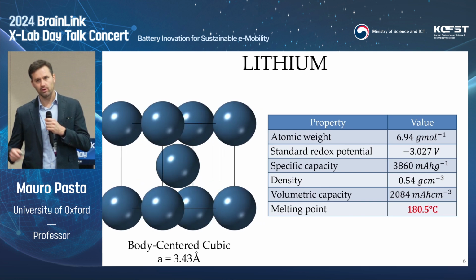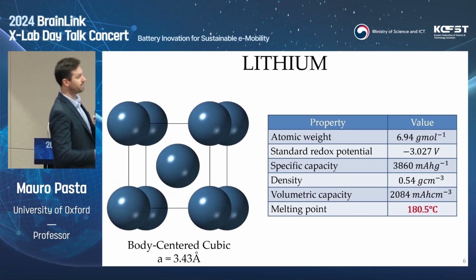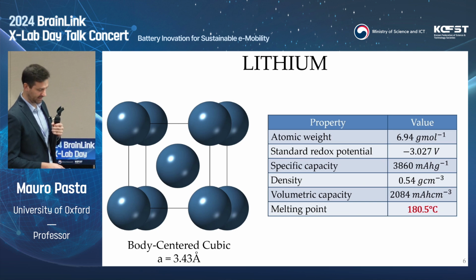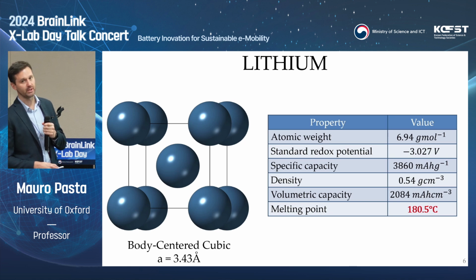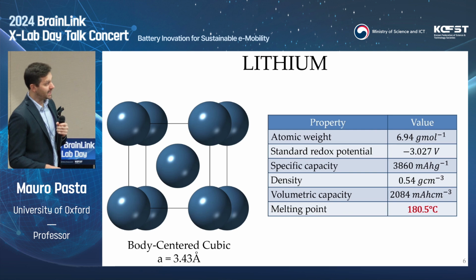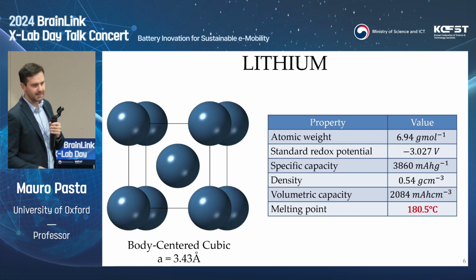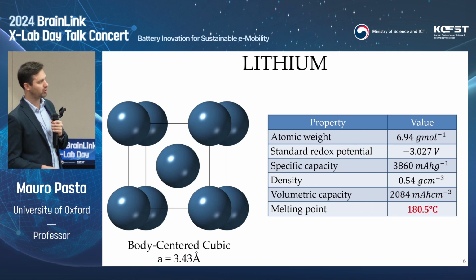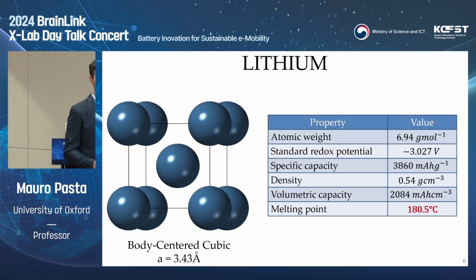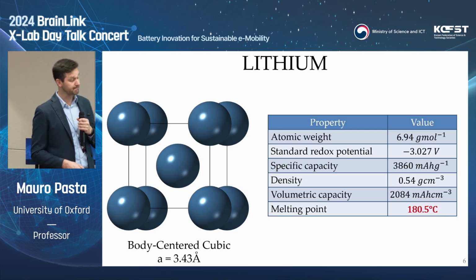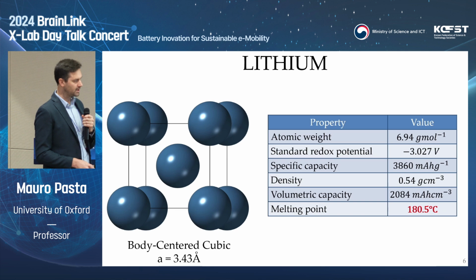Now, the prototypical material of this class of beyond lithium-ion chemistry battery systems is metallic lithium. Metallic lithium is common in most of the beyond lithium-ion chemistry that I mentioned earlier. And the reason why is explained in this little table. It's a BCC metal, it's the lightest metal, about 7 grams per mole. Standard reduction potential is the lowest, so the combination of both results in very high specific capacity, about 10 times higher than the capacity of graphite. Also, a very important property is this melting point that is only 180.5 degrees Celsius, and that's influencing and affecting quite a bit the mechanical properties of lithium itself, and we'll talk about mechanical properties in a few slides.